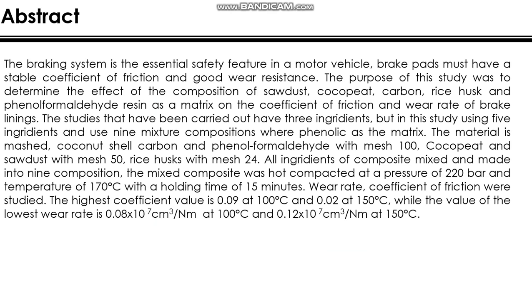The highest coefficient value is 0.09 at 100 degrees Celsius and 0.02 at 150 degrees Celsius, while the value of the lowest wear rate is 0.08 multiplied by 10 to the power minus 7 cubic centimeter per newton meter at 100 degrees Celsius and 0.12 multiplied by 10 to the power minus 7 cubic centimeter per newton meter at 150 degrees Celsius.